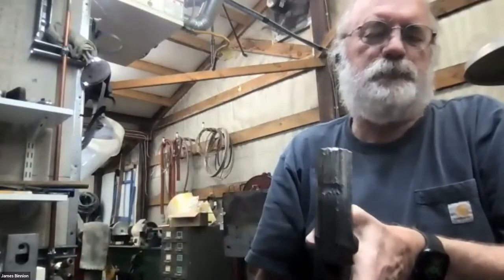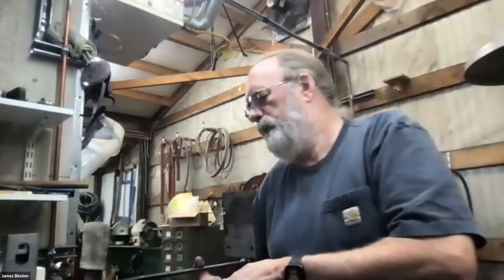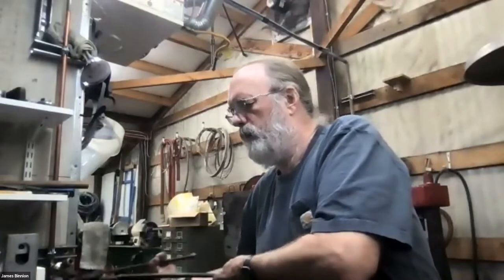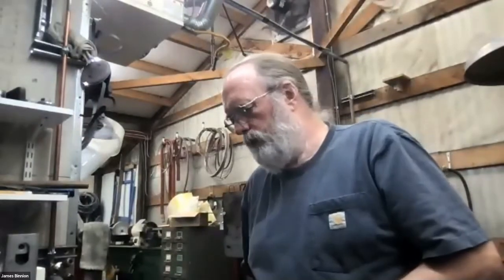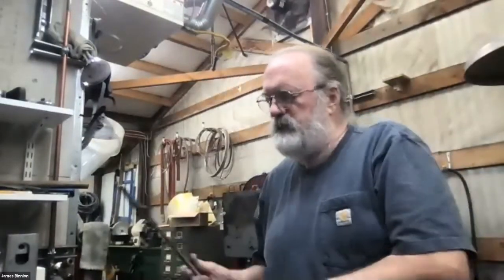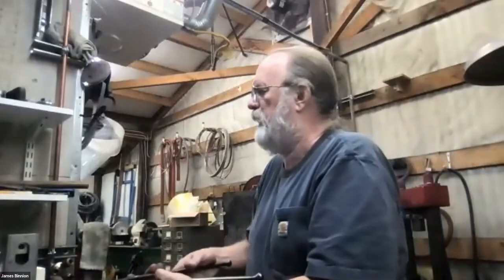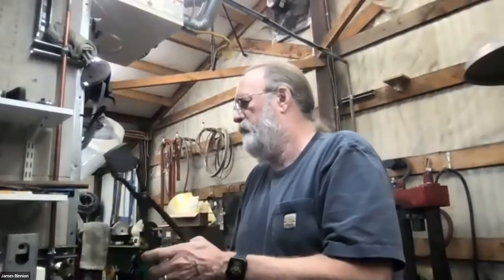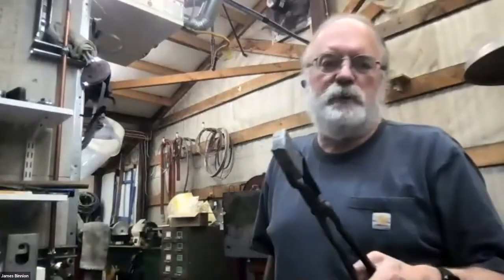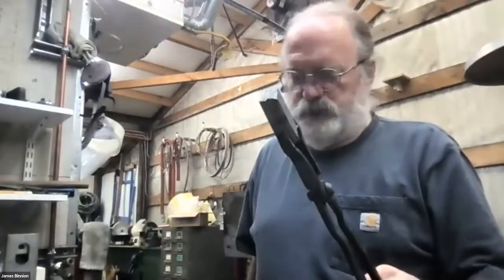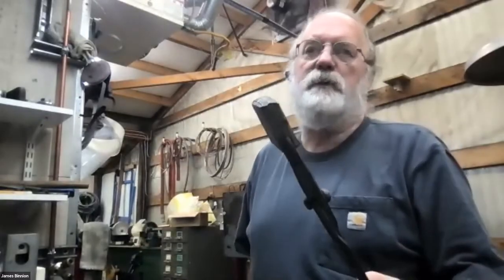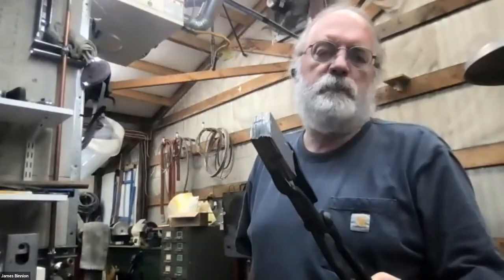on the back side of the cut. Mm-hmm. And do you wait to do that cutting until you've gotten it down to that 50% thickness? This is about the point that I would do that cutting. So I'm pretty close to 50% reduction on this billet right now.